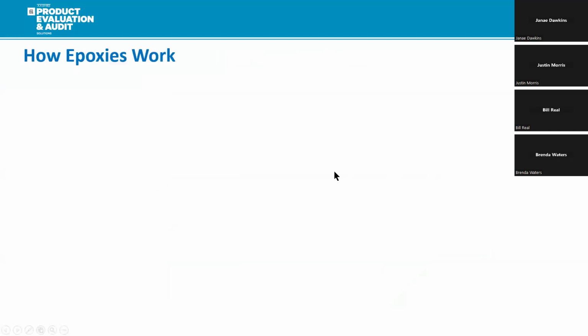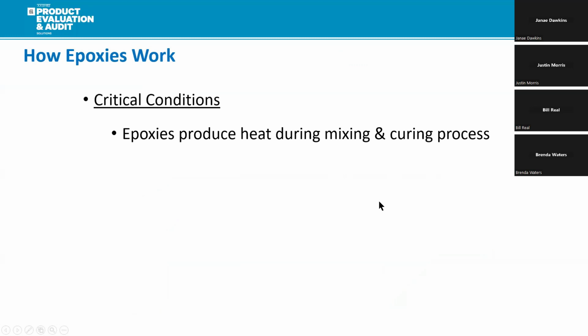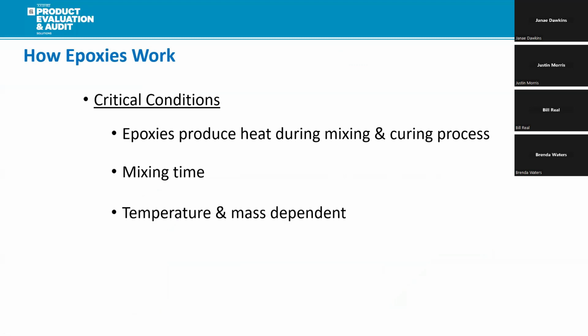So some critical conditions of your epoxies. These epoxies generate heat during the mixing and curing process, so your mixing time is obviously very important. Refer to your manufacturer's recommended mixing instructions whenever you're looking at your mixing times, and they're also mass dependent. So mass and temperature dependent.